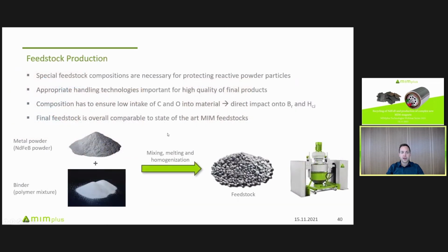The powder can then be used to produce the so-called feedstock. Therefore, we take the metal powder, mix it with suitable organic components, mix it at elevated temperature, and disperse it in a compounding machine. And then you get a good homogeneous mixture, and then the pelletizing step can follow, and you get a feedstock which looks like that.